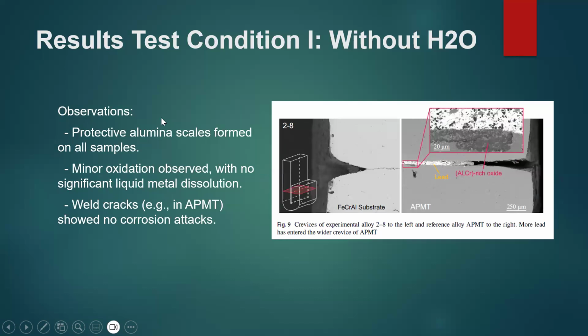The observation is a protective alumina scale formed on the sample, with minor oxidation observed and no significant liquid metal dissolution, while weld cracks in APMT showed no corrosion attacks. So we can see in APMT there are no corrosion attacks.